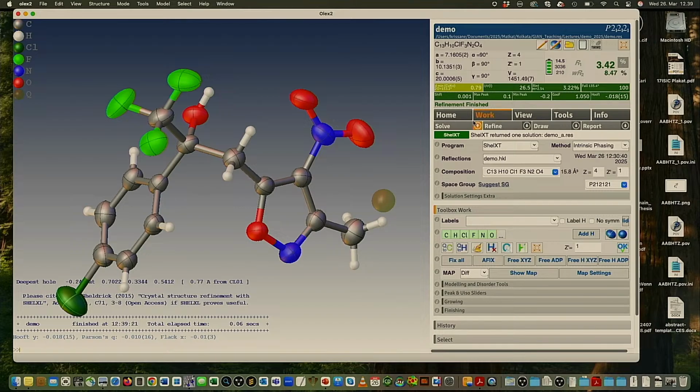And adding one hydrogen makes our structure completely incorrect. It cannot be correct chemically, but this number doesn't change virtually at all. So all the numbers were green, everything is fine, except there is the remark. So you have to be very careful when you analyze the structure, that it is chemically reasonable. Because the X-rays don't know. They don't know what atom is and where is atom and so on. It only looks for the electron density. And we were not looking for the electron density in this area. It was just a computation what the computer was doing, the program.